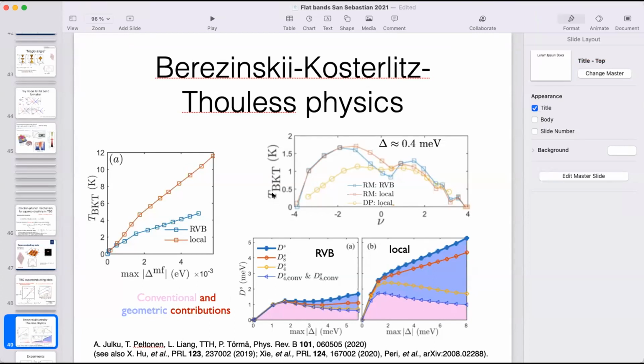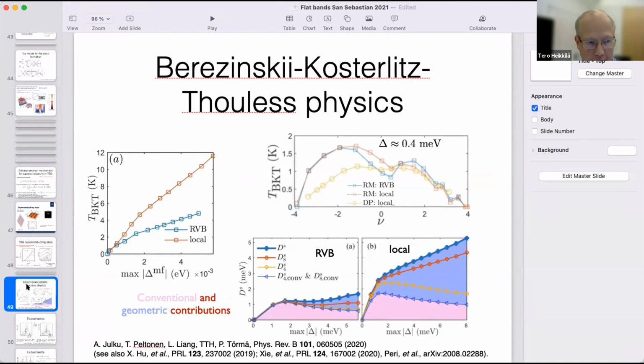So that assumes that essentially the order parameter is s-wave, because you are going to use the Kosterlitz-Nelson relationship, right? But if it's not the standard BKT thing, then it's more complicated. I guess so. Yeah, it's not that equation. This was not a simple calculation, because this is calculating the superfluid weight in the case of this 10,000 atom unit cell, as a function of different parameters. And you are right, most likely one should go even beyond that for twisted bilayer graphene. The three-layer graphene and the Bernal bilayer are much simpler in this sense.